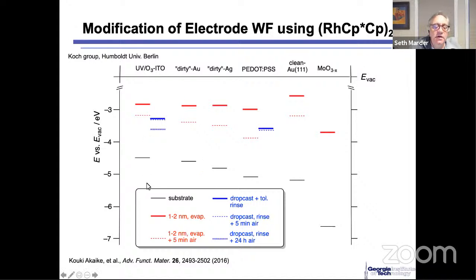So what they do is they have a substrate that has a certain work function, and that's shown by the black line. You can see here a variety of different materials: ITO, gold, silver, PEDOT, clean gold, moly trioxide. Those are the work functions in the absence of doping. Then in red, they evaporate 1 to 2 nanometers of the dopant on that surface. In blue, they drop cast in toluene.